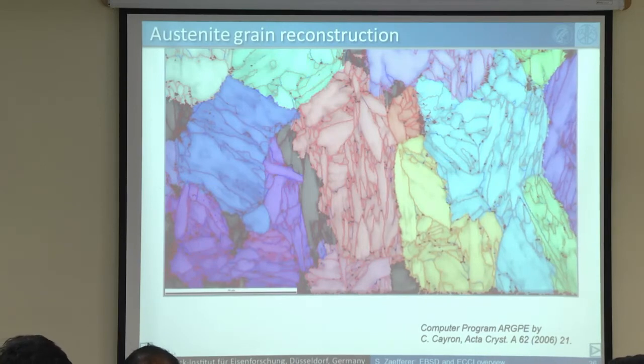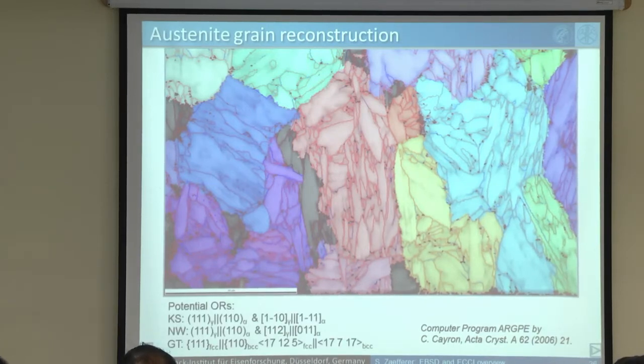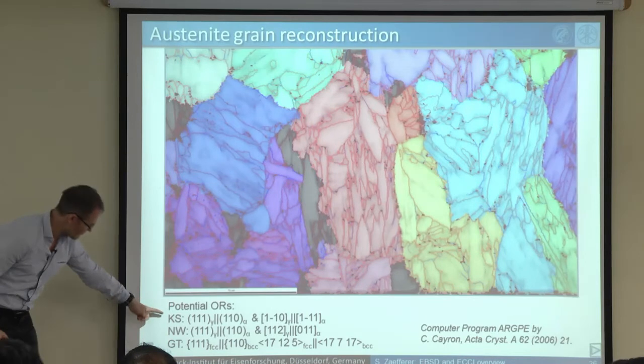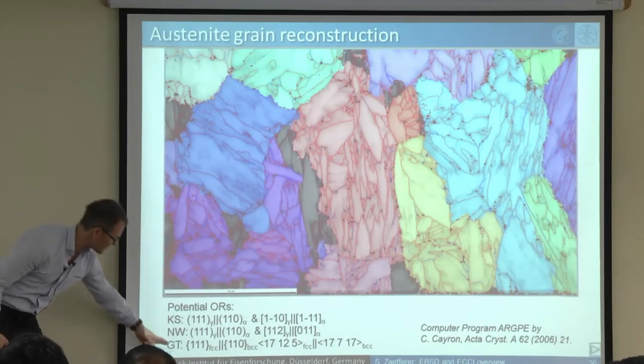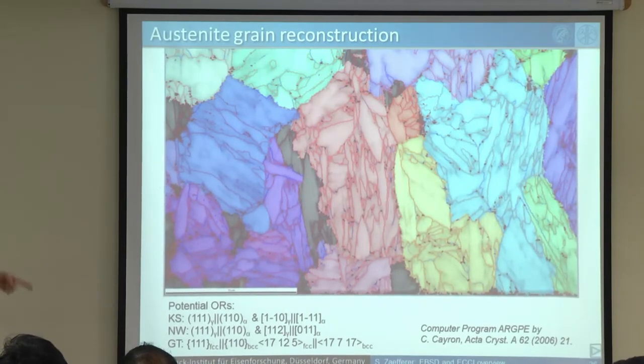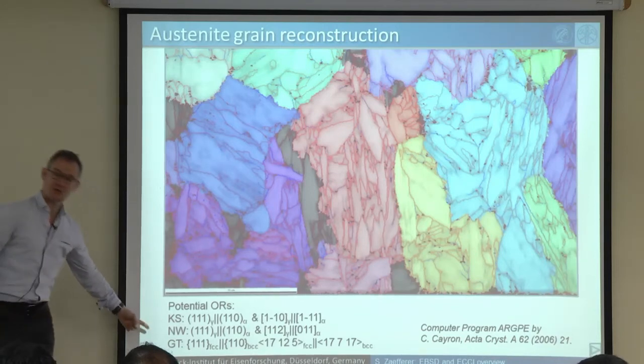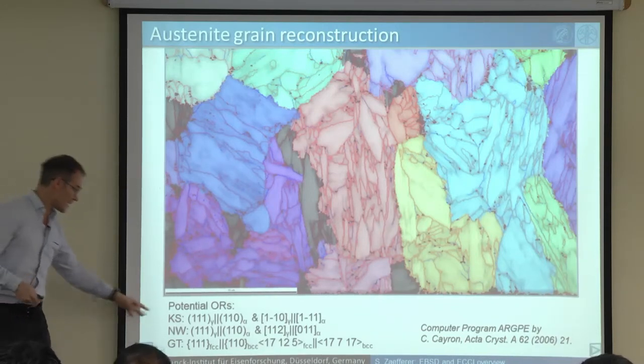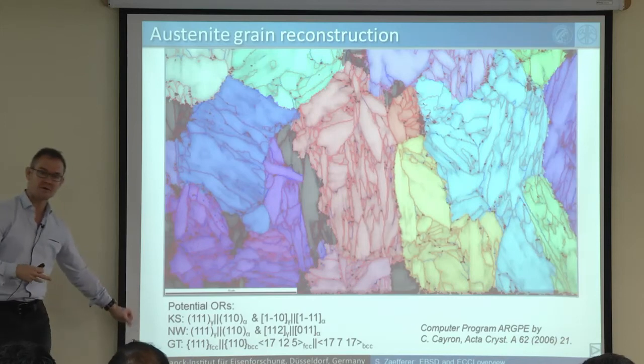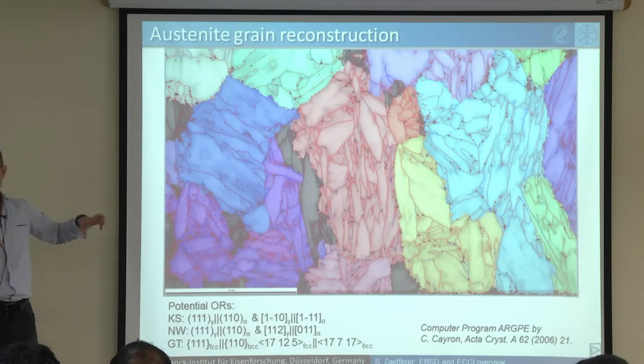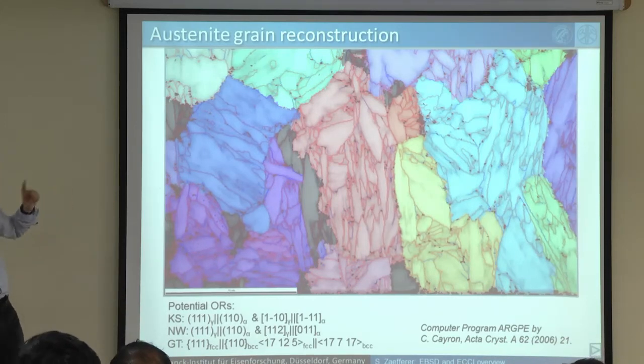Very nice. That is one application, and for this you need to know whether it's Kurdyumov-Sachs or Nishiyama-Wasserman or Greninger-Troiano, this orientation relationship. But then once you have put it in, you can understand more. You can also search for the orientation relationship, yeah, and you find out, it's more KS or more NW, or it's more something completely different. And from this, you understand more how the material actually transforms, yeah.